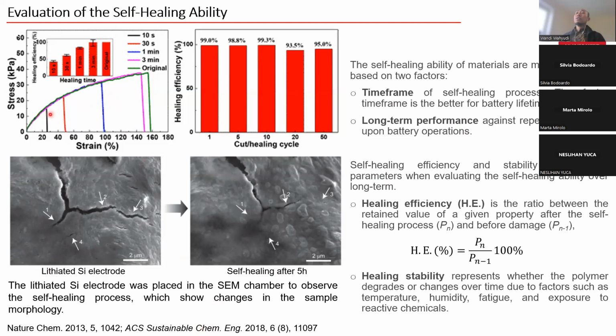The authors show the tensile test of their materials until the material is damaged, and then they wait. After 10 seconds, it recovers less than 50% of the initial strength. After 30 seconds, it could self-heal better, and after 3 minutes, it performs with better recovery ability, which means that it has better healing efficiency.